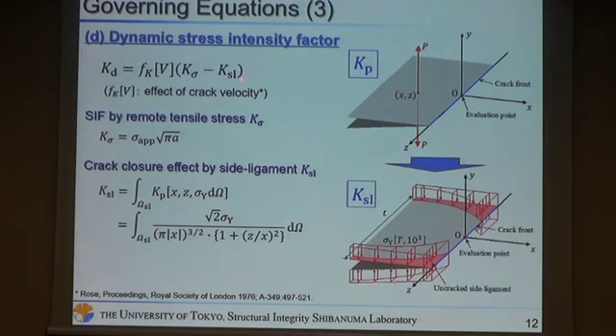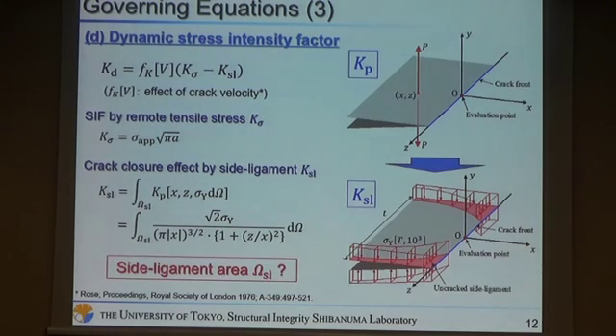The dynamic stress intensity factor is calculated as the stress intensity factor by remote tensile stress minus the crack closure effect by the side ligament. The crack closure effect by the side ligament is calculated by integration of the stress intensity factor by a point load at the surface of the crack, like this. And the remaining problem is the area of the side ligament.